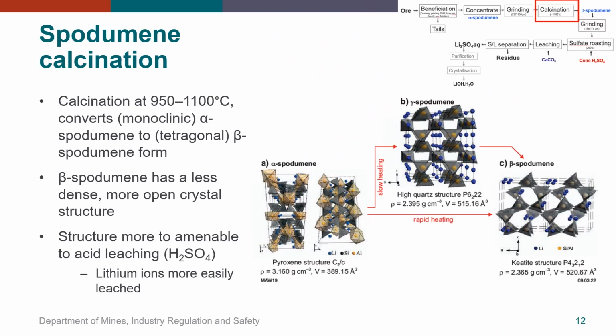We'll now look at the impact alteration has during the processing calcination stage. Spodumene, as the monoclinic alpha form, undergoes thermal transformation to the tetragonal beta form in the temperature range 950 to 1100 degrees. The image on the right shows the reaction pathways during heating, which can form an intermediate gamma spodumene phase depending on the rate of heating.